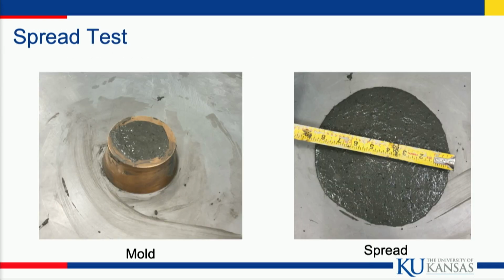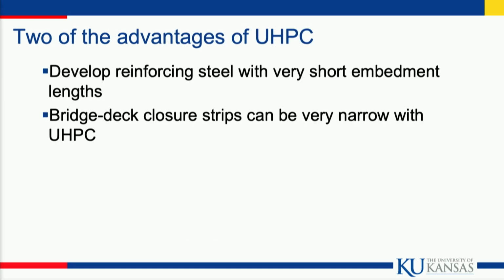Here we see a spread test. We put it in the mold, and then we pull the mold up, and it spreads, in this case, to about 8.5 inches. Some of the advantages: when we typically splice rebar, you're looking a lot of times at a splice of 2-3 feet. When you start using this high-strength UHPC material, you can get it down to a few inches. And when we make precast elements, like accelerated bridge construction, ABC, you could get these panels really close together. So that's a tremendous advantage.